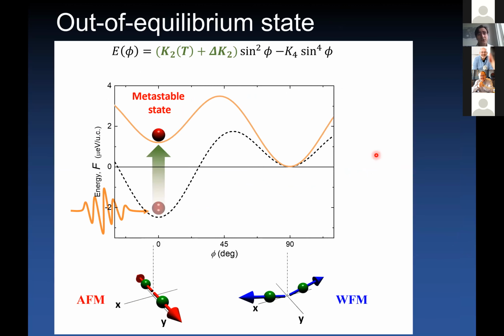Okay, so by measuring spin precessions in and out of equilibrium in our system, we are able to resolve the actual shape of our magnetic potential. We can directly see that by exciting our system in the antiferromagnetic phase, we can create a metastable state where the antiferromagnetic state is no longer the absolute minimum of the system. So the question is, can we excite the system with a large enough amplitude that the system can switch from this metastable state induced out of equilibrium to the ferromagnetic phase, the weak ferromagnetic phase?